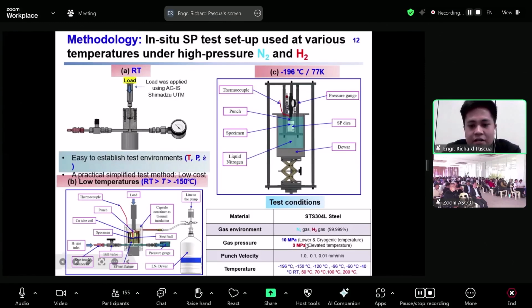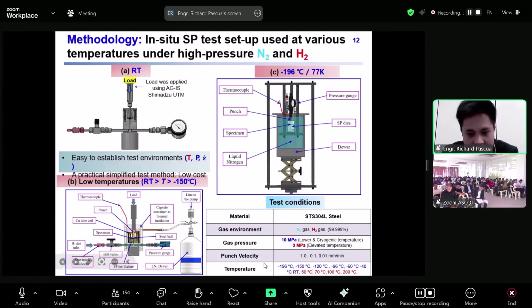For the gas pressure, we used 10 megapascal high pressure at lower temperature and cryogenic temperature, and 3 megapascal for elevated temperature. To evaluate the deformation behaviors of the material under the hydrogen environment, we implement 3 different punch velocities from 1.0 to 0.01 millimeter per minute. And we evaluate the hydrogen embrittlement behavior of the material in a wide temperature range from negative 196 degrees Celsius to 200 degrees Celsius.